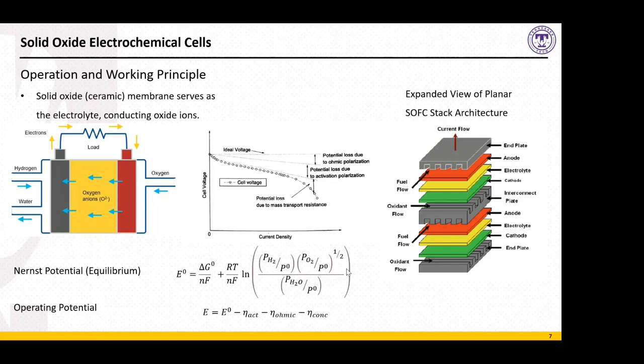The Nernst potential is the equilibrium voltage of a given reaction set within a fuel cell. In addition to this, a fuel cell, when it's actually operational, will have certain losses that come up in the form of the finite reaction kinetics. That's accounted for in the activation overpotential. You have the ohmic overpotential, which accounts for the resistivity through the conducting portions of the cell. And then you have a concentration overpotential as well, which is, again, due to the finite speed of gas diffusion through the electrodes to the reaction sites.